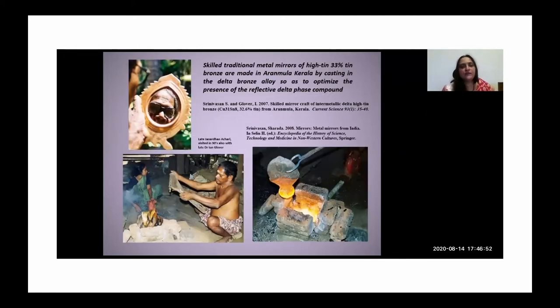Okay, so now I'll take you through some of the steps of actually making these mirrors. And you're looking on top at a photograph of the late Janardhan Achari. He was one of the master craftspeople. And this tradition of making metal mirrors still survives in Aranmula in Kerala, where they made these mirrors of 33% tin bronze, basically by casting this delta bronze alloy to optimize this reflective phase, but also they were able to overcome some of the problems of brittleness, because this alloy is actually very brittle. The whole aim of the way they were casting and making it was to optimize the specular property, but minimize the brittleness.